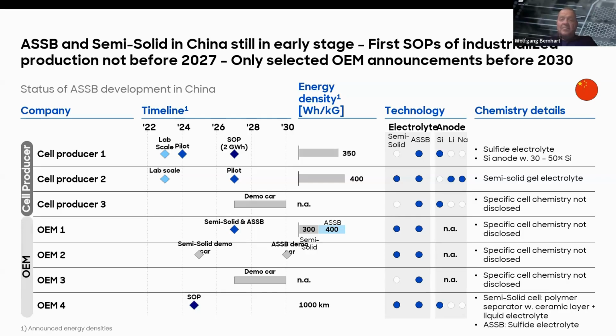Slightly higher energy density with a semi-solid electrolyte, but interestingly enough, also looking at sodium ion combined with solid state technologies. And then there's a third one. That's not really clear what the cell chemistry is. We were not able to get that. We have various OEMs. Again, they plan to come to the market with demo cars mainly. But as you can see here, even that is for the time being mostly in the demo stage, and the only one that's coming to the market is actually a solid state polymer separator with a ceramic layer and a liquid electrolyte, and then a sulfide electrolyte in a second step. They didn't mention the energy density. I think it's not that much higher than what we do see currently.